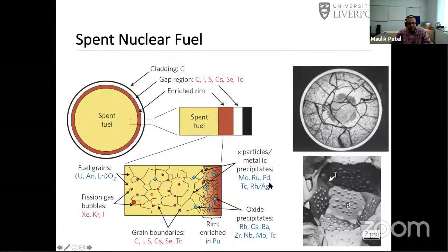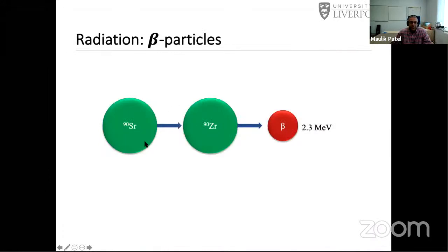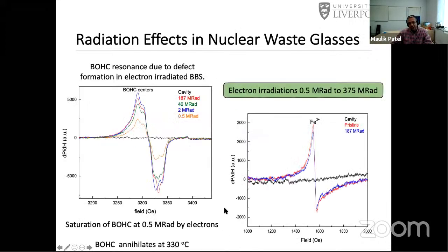Okay. Coming to spent nuclear fuel. In spent nuclear fuel, you have some fission products like strontium and cesium, which decay by beta in the first 30 years. And when electrons pass through materials, they cause lots of ionization. In these barium borosilicate glasses, which are used as nuclear waste immobilization in India, they cause different defects that lead to changes in their stability. What I mean by stability is that you want a nuclear waste encapsulating material which is absolutely leach resistant, meaning if you put it in water, in a highly acidic water environment, it should not degrade, it should not leach out, it should not corrode. And these defects either enhance or degrade the leach resistance, which is the durability of these glasses.